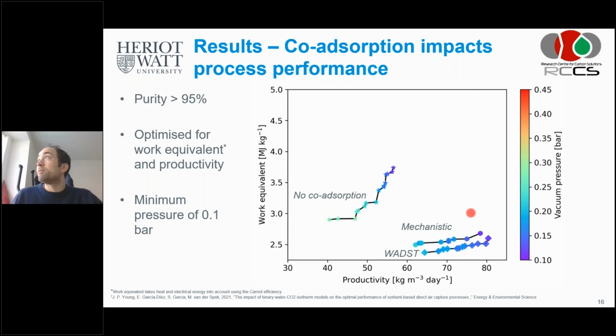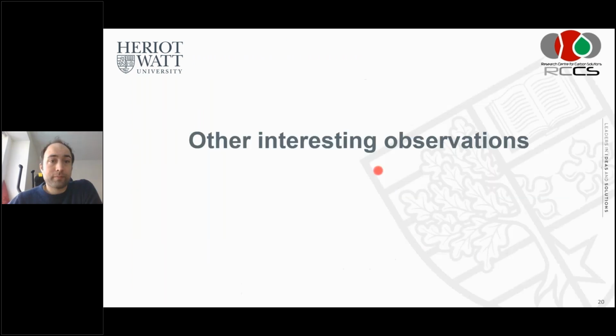And I talk quite a bit to people in the direct air capture industry and also in the adsorbent industry, and water CO2 co-adsorption is really the important thing to get much more data on at the moment, because for many adsorbents that data is not available. So if anybody is developing adsorbents, by all means also try to report the water adsorption isotherms on your adsorbents, and if you can, also measure the water CO2 co-adsorption. We really need it for process design.